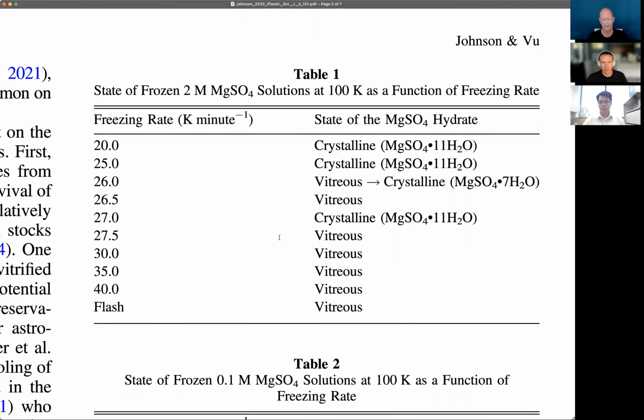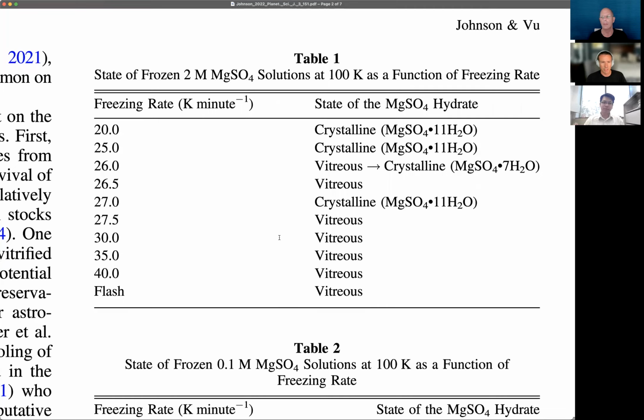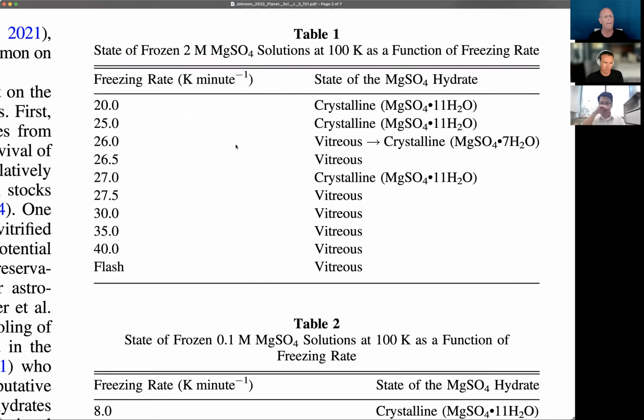Basically, we're starting to step through the freezing rate at fairly fine half degree steps. So we're getting into the experimental limit of how well we're really controlling our temperatures. When we're passing through the critical rate where you pass from glass formation to crystal formation, we're sort of hitting it or missing it.